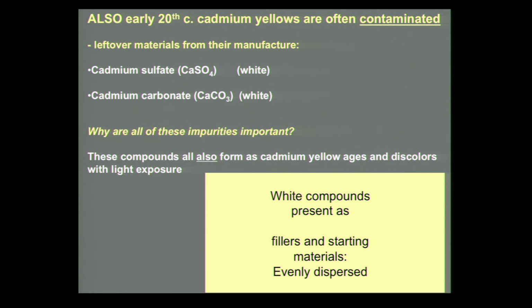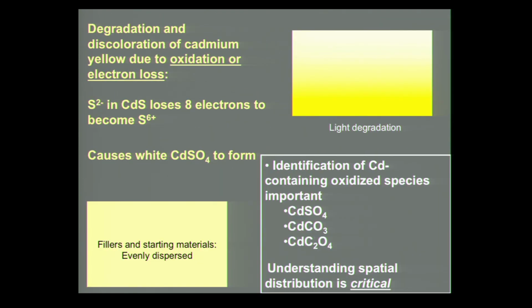And so when the white compounds are present throughout the paint layer, when they're evenly dispersed, like I've shown here, then they're likely fillers and starting materials. On the other hand, if the white compounds are present at the top of the paint layer, then they're likely due to photodegradation or degradation due to exposure to light.